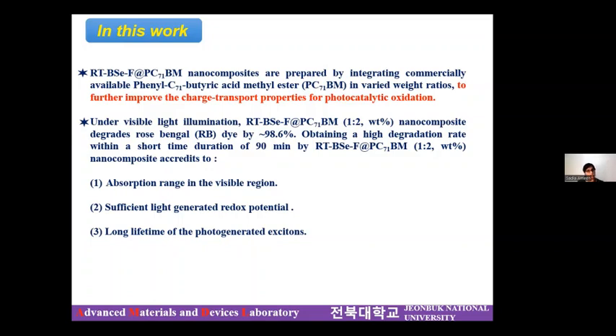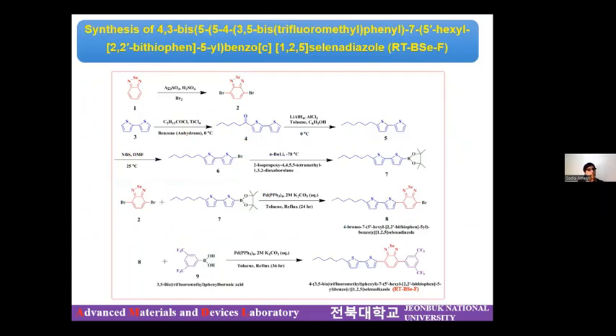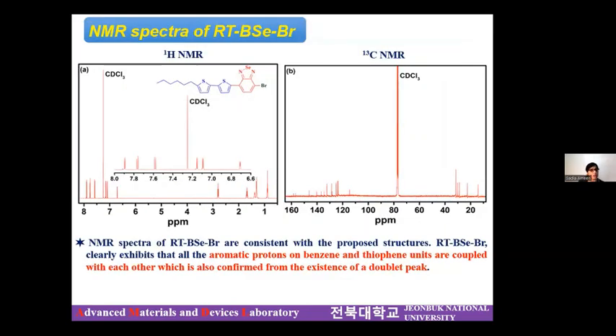We think these nanocomposite materials are effective because they show an absorption range in the visible region, sufficient light-generated redox potential, and a long lifetime of the photogenerated excitons. This is a brief description of how we synthesized the molecule. I'm not going into details. As you can see, synthesizing small organic molecules is itself a difficult job because it involves the synthesis of several intermediates, and through those intermediates, we obtain the final products. It is also very significant to characterize each and every intermediate obtained during the reaction so that we can confirm the structure has been made, and these intermediates are further used for obtaining the final desired material. This is how we did the characterizations for the intermediates, through proton and carbon NMR.